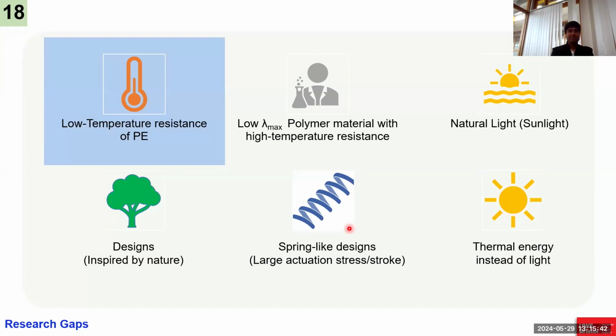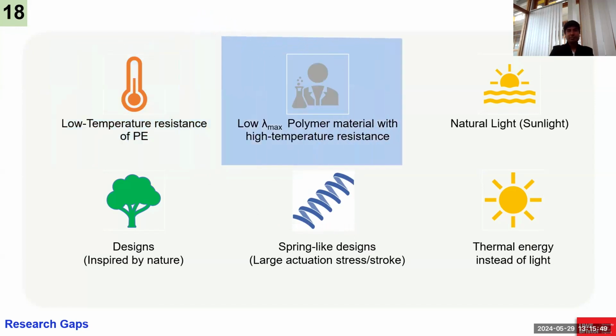So it is a limit in terms of polyethylene, but that means we can use other materials, because we saw that lambda, like the draw ratio, is not playing a very significant role here. So we can use polymeric materials with high temperature resistant properties, such as polyamide, polyester, that can resist heat much better as compared to polyethylene, and at a lower draw ratio. So we can explore that.